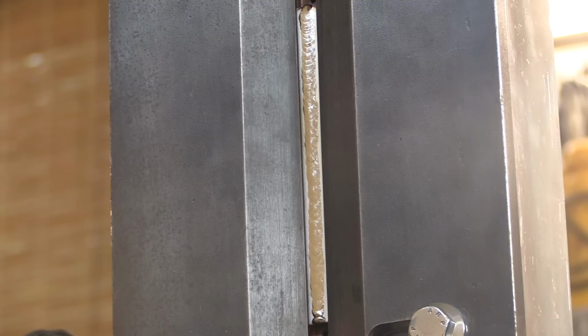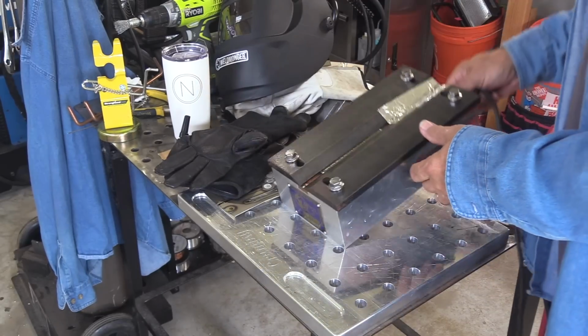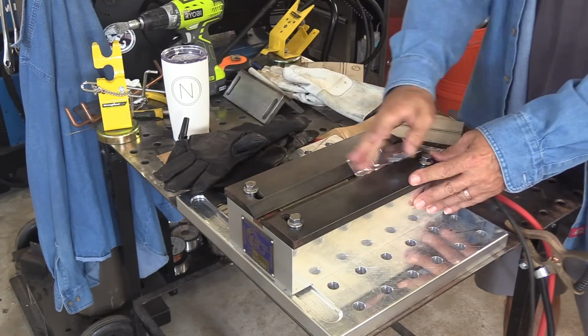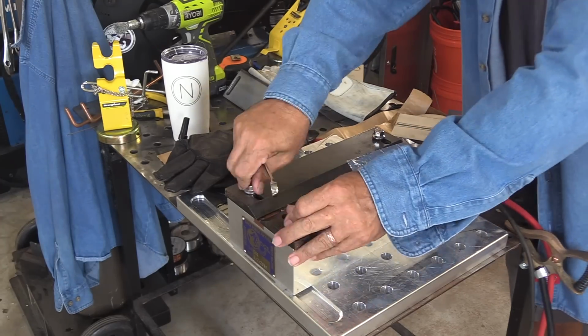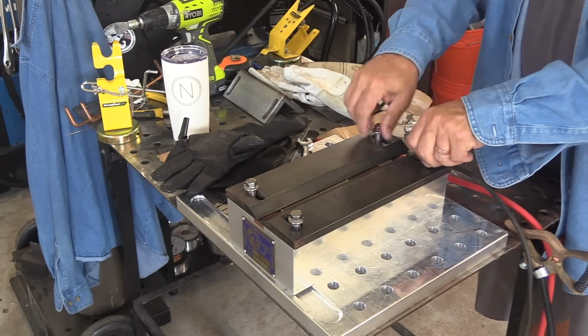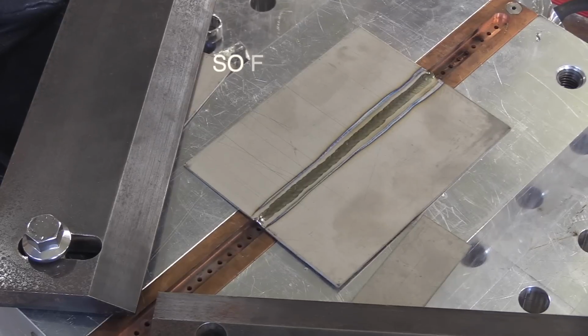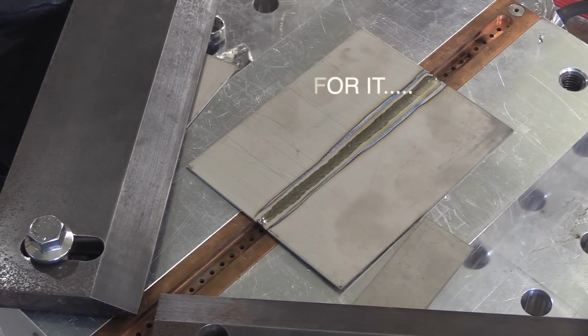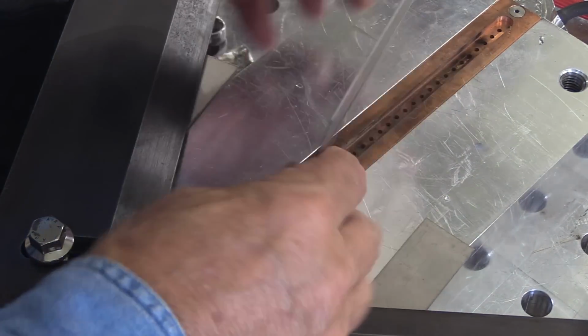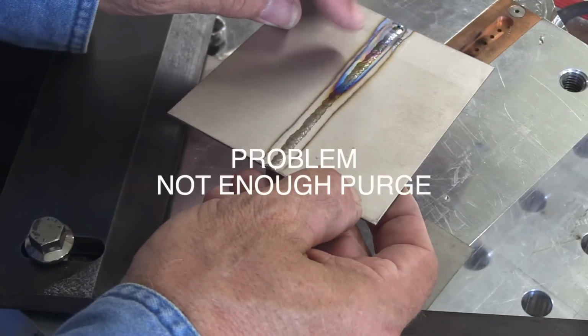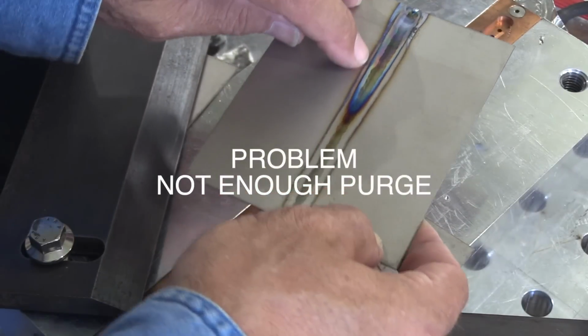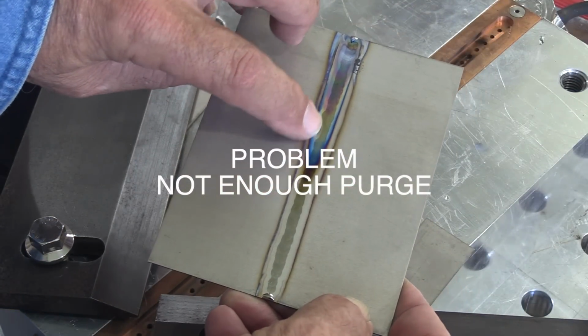Well, that doesn't look too bad, but we'll take it out of the fixture and check out the penetration side. Make sure we got full penetration and check out the purge quality and see what we got. So far, the front side looks pretty good. We'll flip it over, and ruh-roh, that's bad. That's not acceptable on titanium.